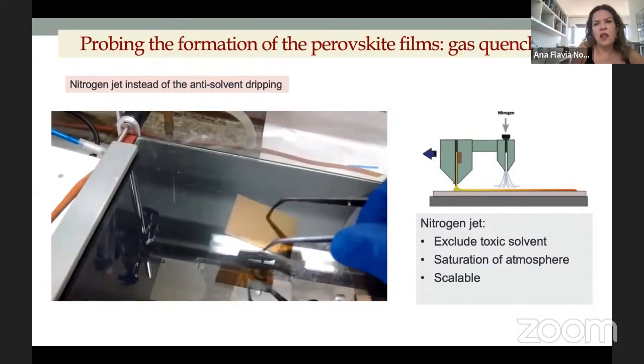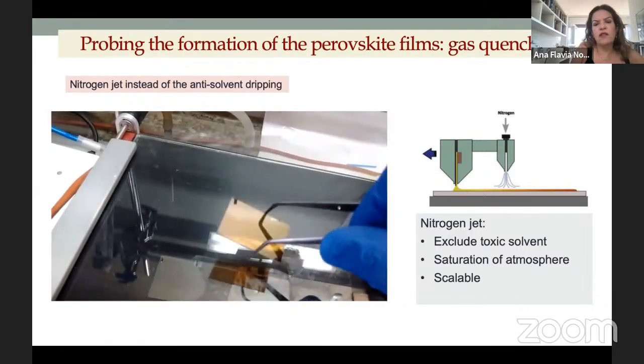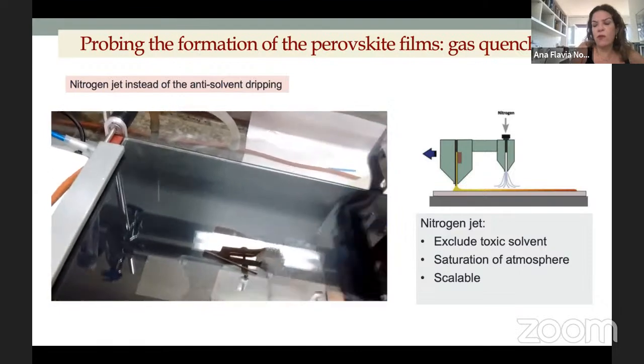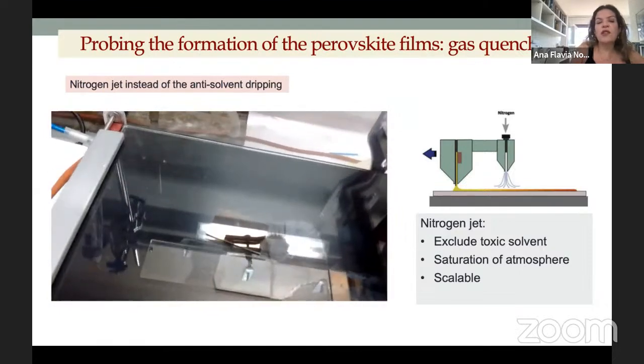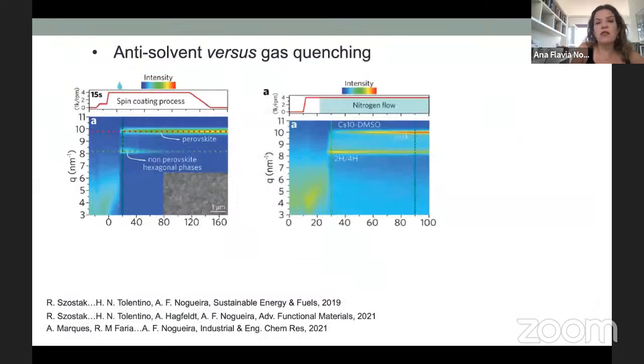Okay, and then you can see here is a very nice transparent film of perovskite. So then we decided to compare both methods. This is the antisolvent versus the gas quenching method. So what we can see here, for instance, this is the result that I showed you before. In this case here, you see that it takes much more time for the perovskites to form.